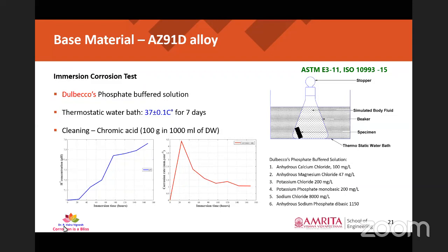Added to that, we monitored the pH of the solution with a sensitivity of plus or minus 0.01. It is found that the hydrogen ion concentration decreases with increase in immersion time. Okay, so pH is minus log of H plus, so it increases with respect to time. This has to be monitored when we implant the material inside a human body. Why? Because generally speaking, the human body has an average pH of 7.2 to 7.4. If it goes well below or well above that, it is also going to be a major drawback if we implant such materials.